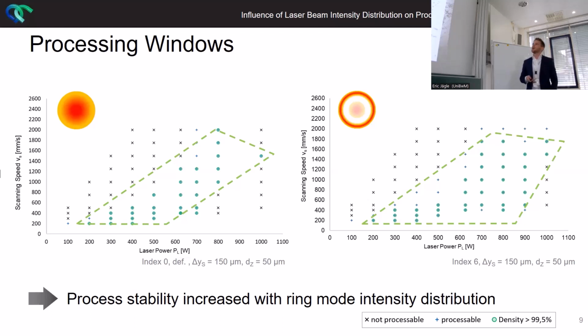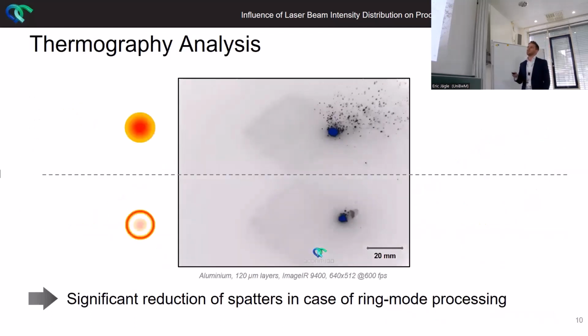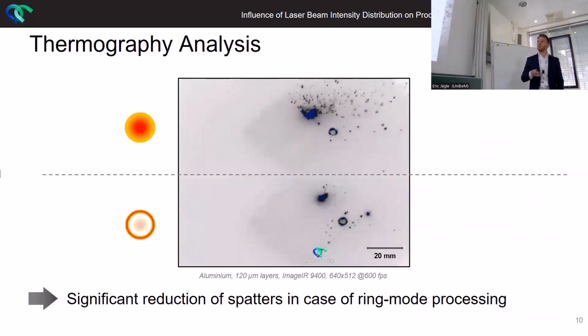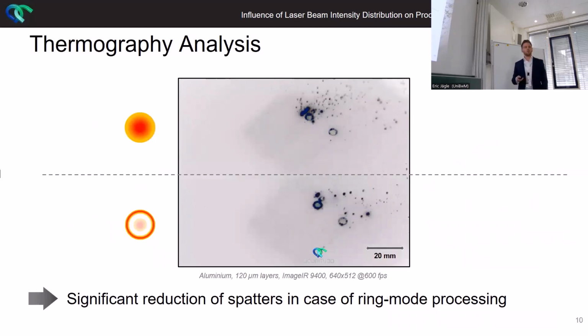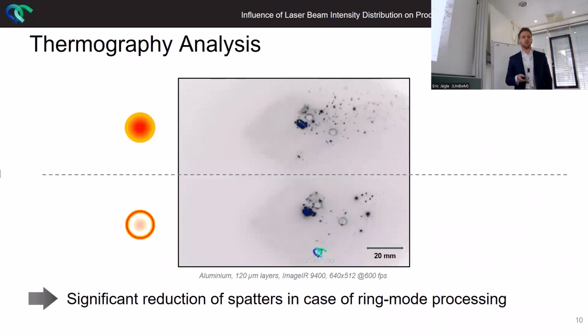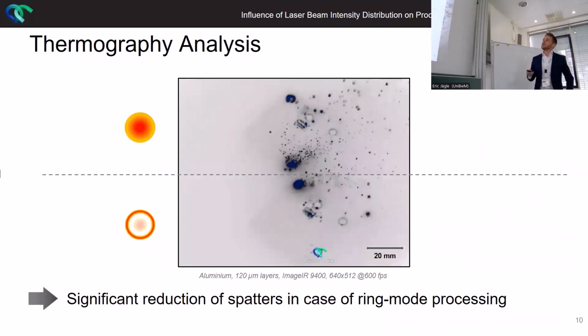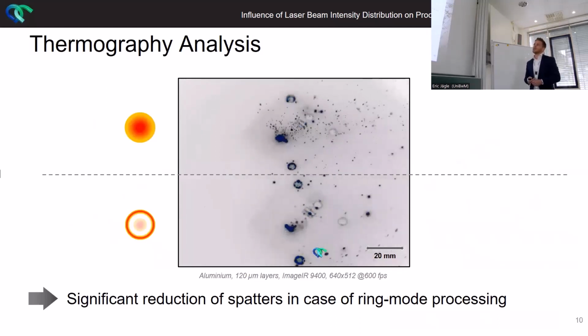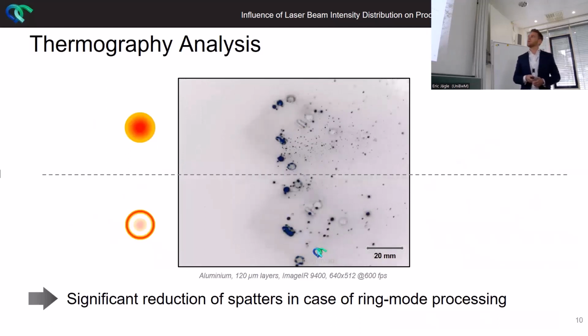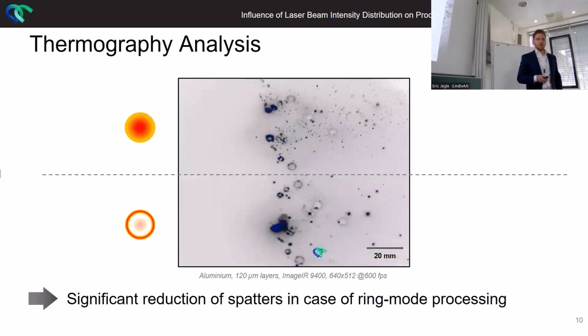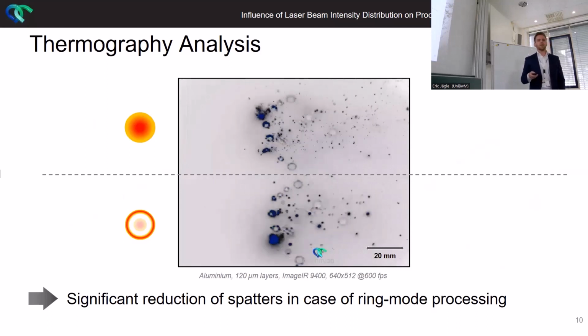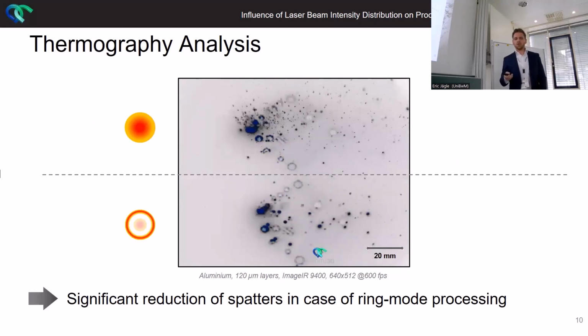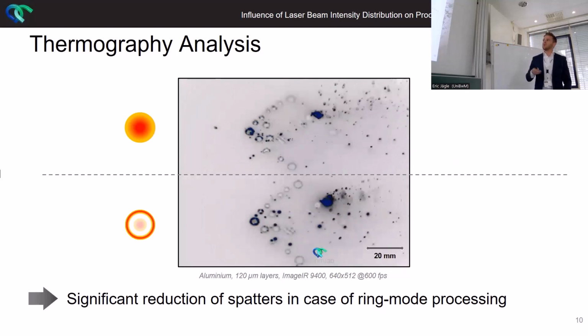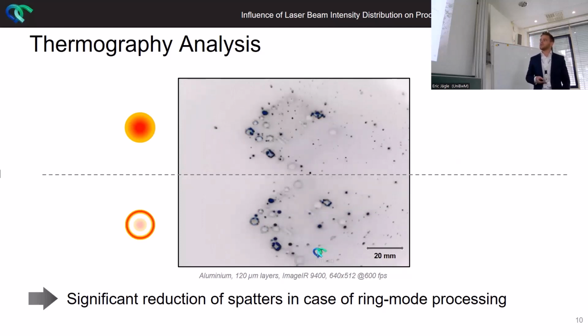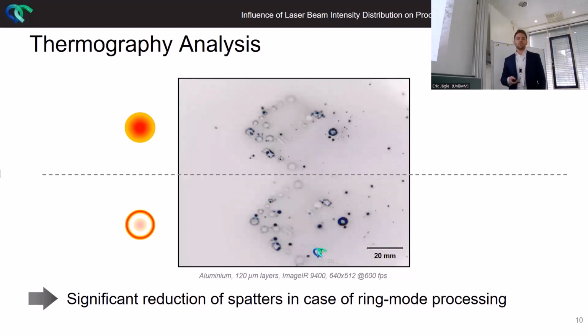But in the meantime, we thought of a more straightforward way to qualify a good process. What always occurs in LPBF is spatter formation. What you can see here is the same geometry printed with index 0 and index 6. This spatter formation can affect your process in two ways: by insufficient melting of a big particle which lands on the not yet exposed area, or by affecting the roughness of your part afterwards.